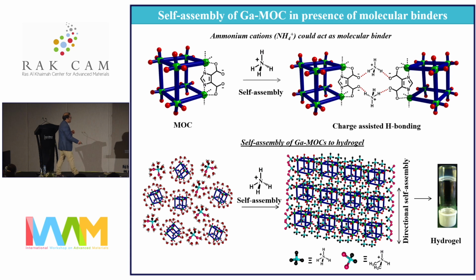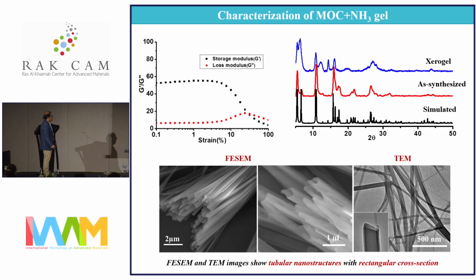When you add that into the aqueous solution, it forms a hydrogel—a transparent hydrogel—with this MOC through propagation via charge-assisted hydrogen bonding interaction.